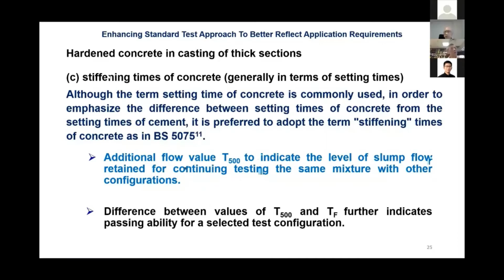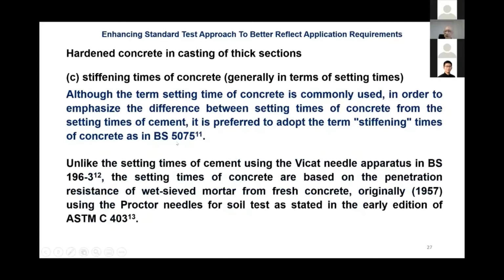Setting is a hydration process that finally reaches solid from a semi-liquid to a solid stage, whereas stiffening means it is in the stage of a liquid transforming to a solid. So I call it stiffening time just to make a difference. Now, in the UK, the BS 5075 used to have this setting time test, which is done in a slightly different way from the original ASTM test, which I did numerical modelling of for my PhD thesis. And so I know this test inside out.